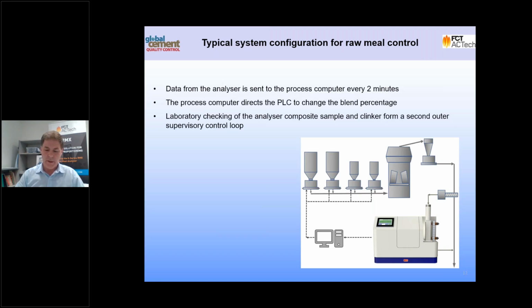So the analyzer provides elemental data to the process computer, which then compares it to its set points for the silicon, calcium, alumina, and iron. Based on those results, the adjustments to the feeders are made and the appropriate changes will happen. By checking a composite material that's passed through the analyzer, any drift can be compensated for. So this composite sample effectively becomes an outer control supervisory loop for the system.